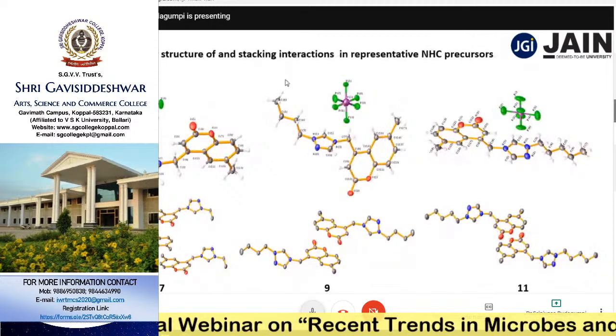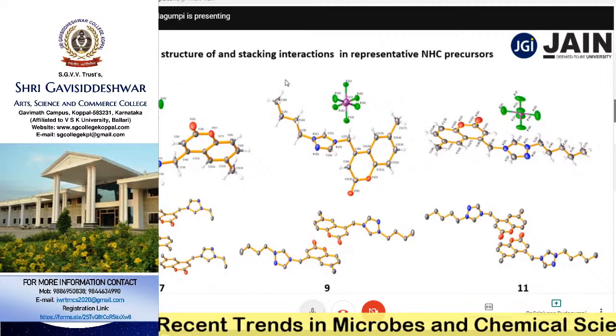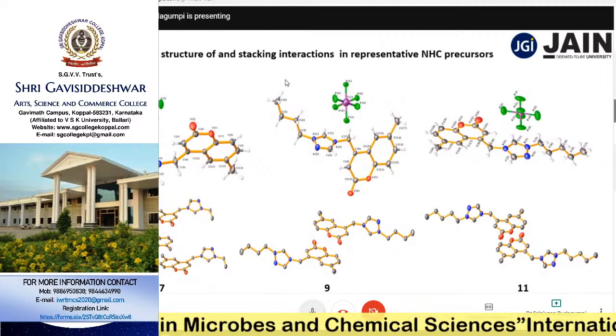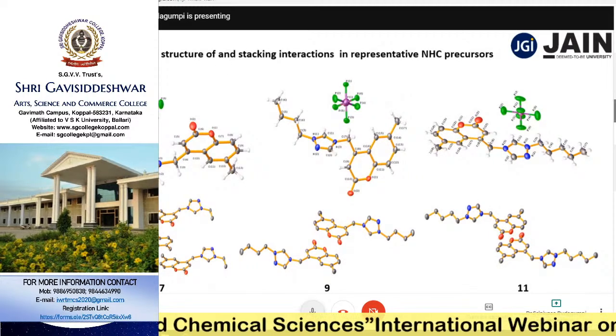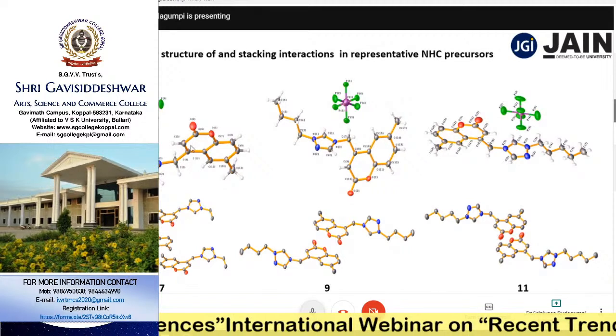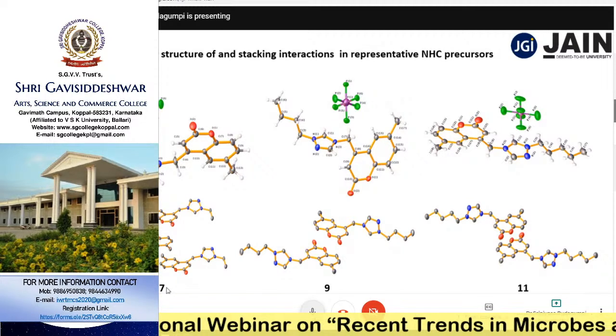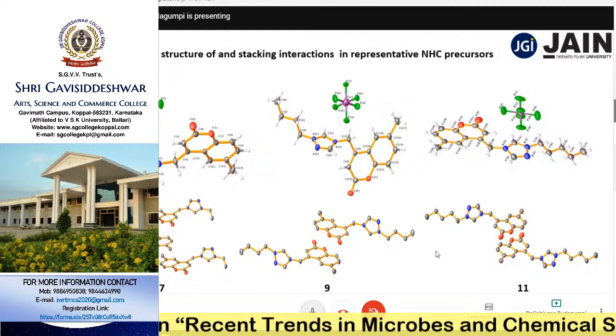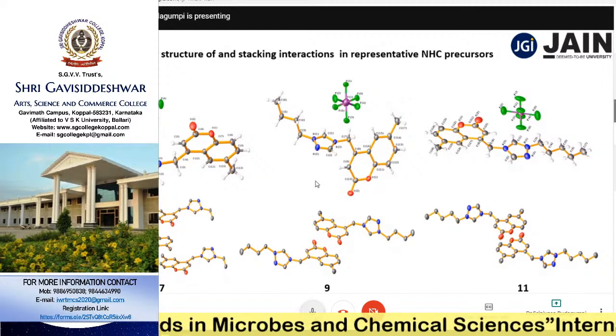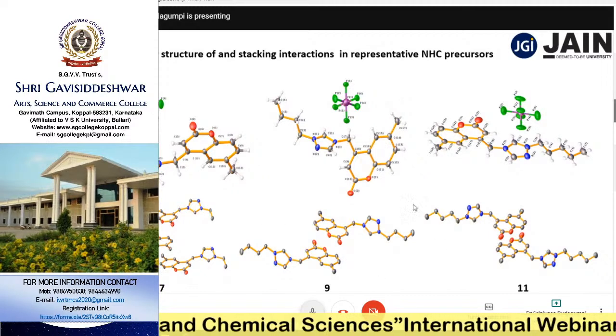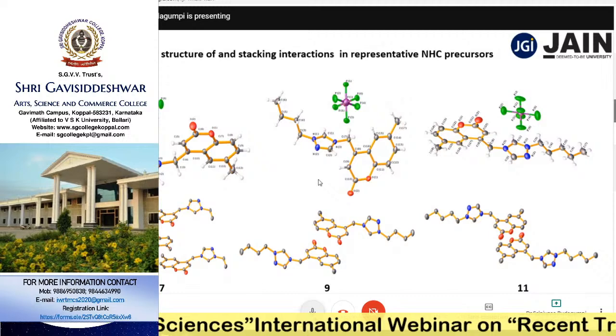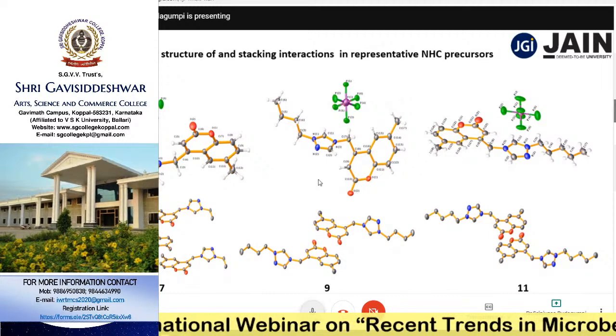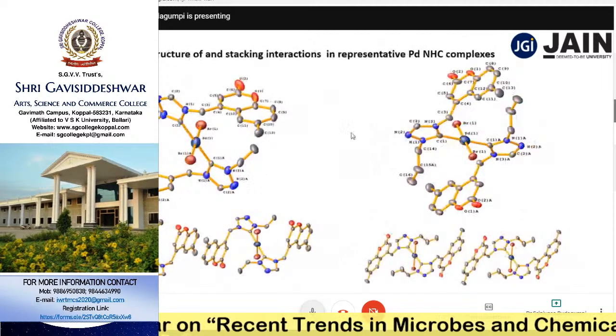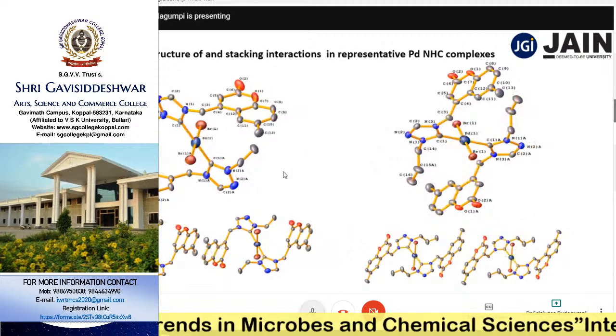Further, single crystal XRD analysis has been done using these salts. So we were able to get the single crystals of 3 salts here: salt number 7, 9, and 11. So these crystal structures clearly illustrate that the salts have been formed unambiguously. Similarly, complexes were also obtained in crystalline form and solved for their crystal structures.